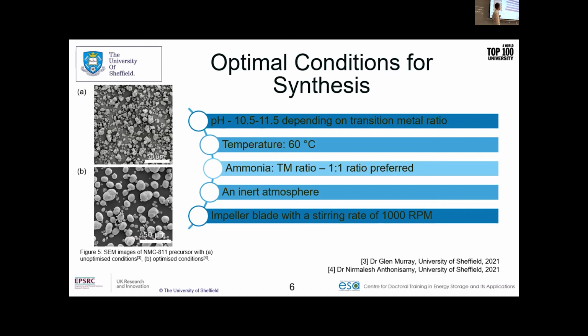So we look at pH, which is widely seen in literature as a very key parameter. We're looking at about 10.5 to 11.5, depending on the NMC ratio. The nickel content within the material alters the chemistry, and we need to adapt the conditions to fit those, because otherwise you won't get these spherical particles due to the differing redox situation within the system.